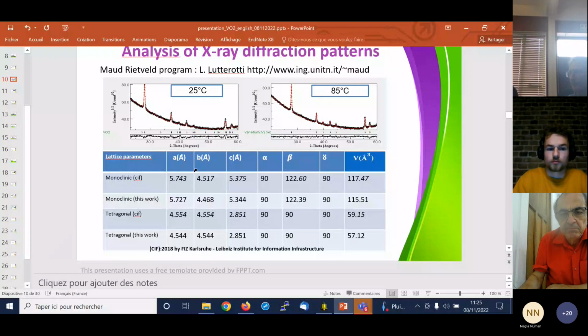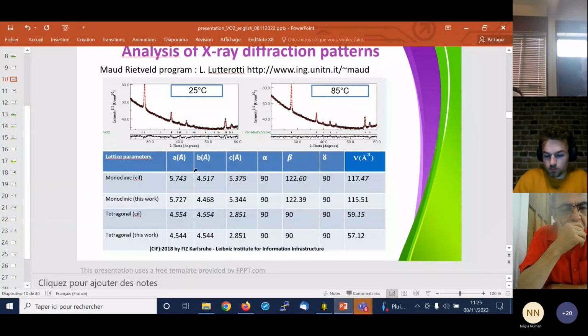So does it distort the whole structure? I mean, when you add 3% of tungsten, does it distort the whole lattice? Yeah, it's distorting the lattice. You don't have the same type of distortion when you replace vanadium by tungsten as if you just have pure vanadium oxide. But we didn't make any DFT calculations. That's not our field. But if you want to do it, that's fine, go ahead. I'm sure it will be interesting. You can try and see what's going to happen. I think some people have already done that, but yeah, go ahead.